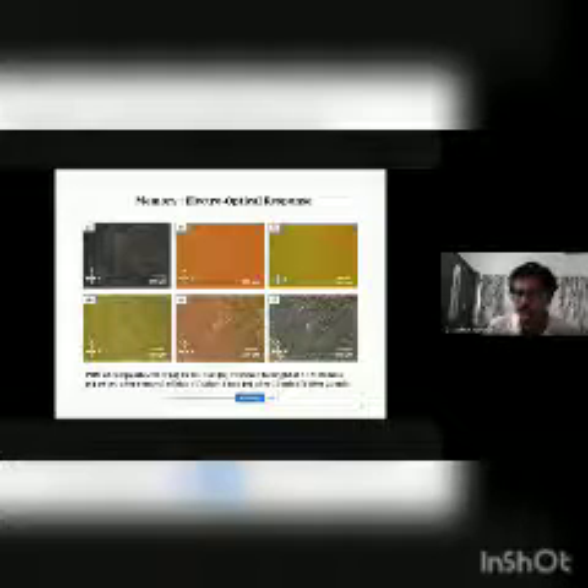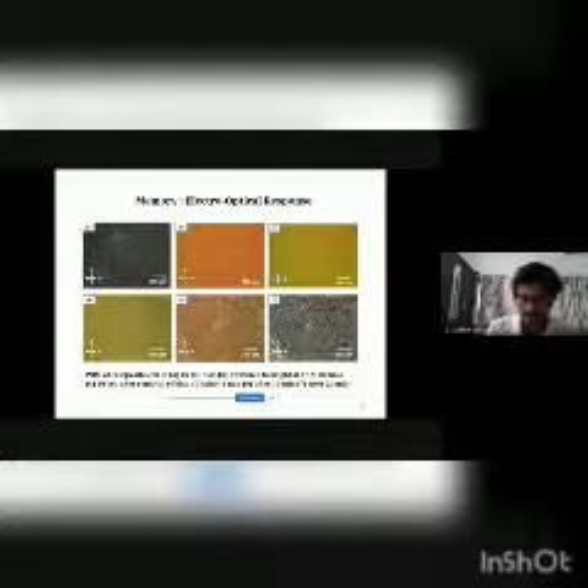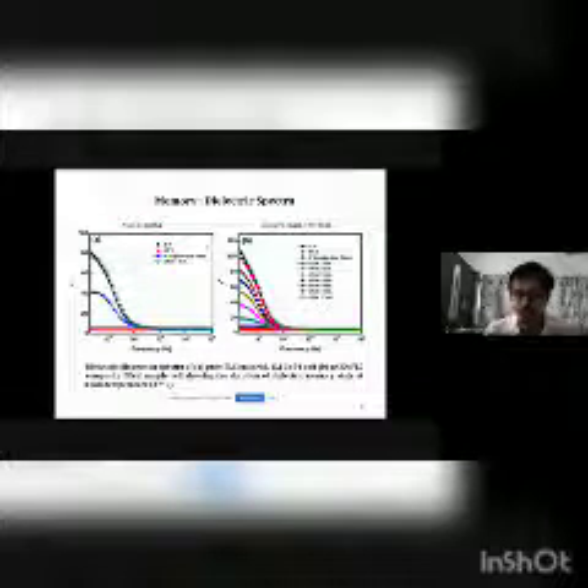So up to 20 minutes, your device is in the switched state, which is showing optical memory. So that's the beauty of your device. Up to 20 minutes, there is no requirement of any power. You only need to trigger it at the initial stage, and after that you can remove the bias. This has been further verified through different characterization techniques like dielectric spectroscopy and optical response.